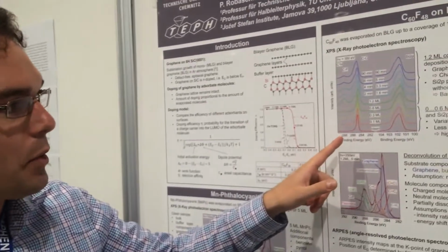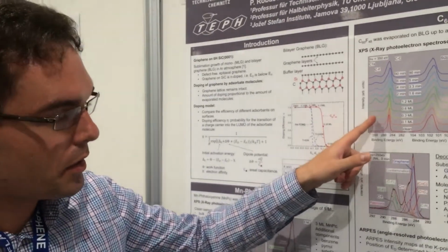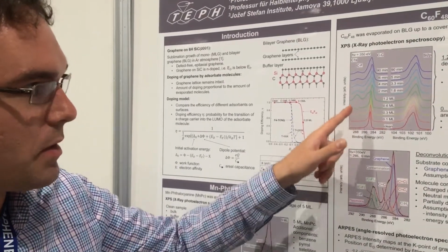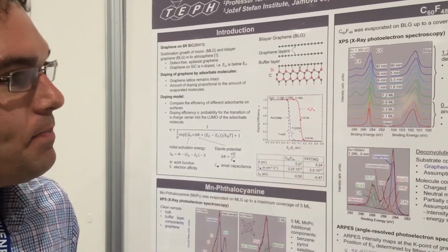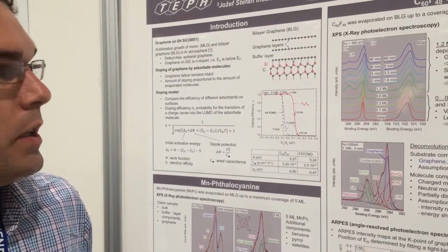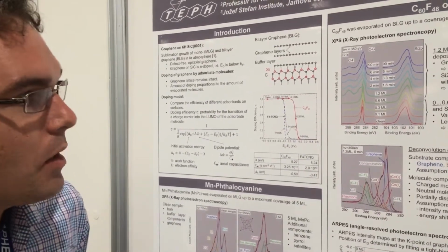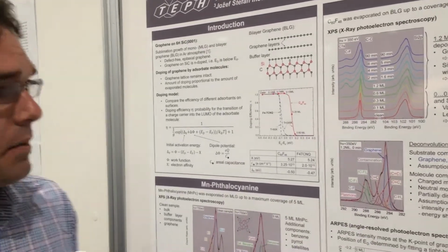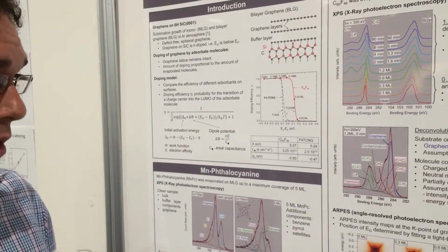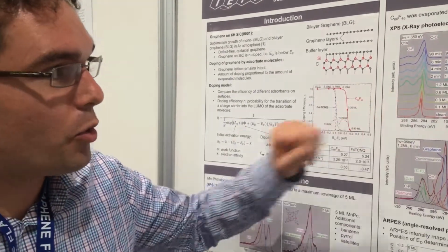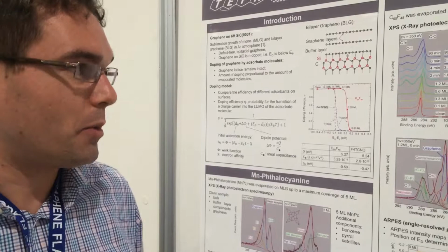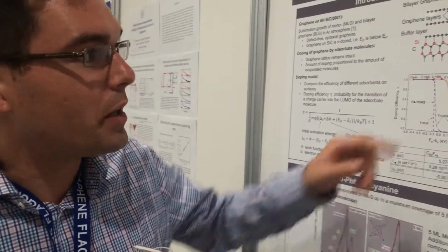So basically what we saw was that there was nearly no peak at the carbon positions where we expected the molecule to be, and also a small amount of graphene shift. From other work we would have expected some more signal and some more shifting, so we evaporated a huge amount, that's 1.2 monolayers, and looked at the time evolution, and we could indeed see, on these positions here,